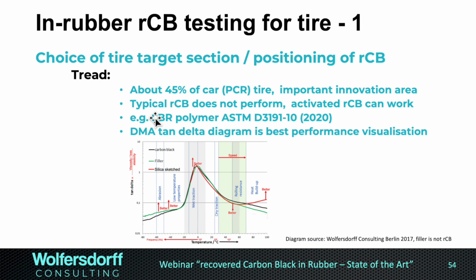Now, how do we test the recovered carbon black for tire? We first need to select the tire section, which determines what kind of rubber polymer and what kind of formulation is used. The tread is, as we've seen, 45% of the car tire. It's an important innovation area. Most of the tire innovation is on the tread, because the tread contributes so much to rolling resistance. It contributes to the grip, and this is really where the tire offers the value.